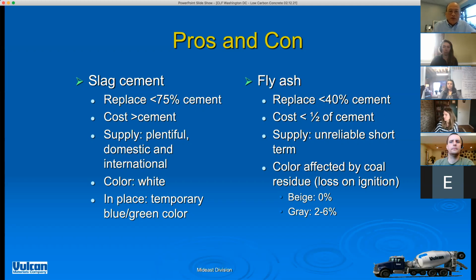Going to the right-hand side, looking at the fly ash comparison, locally fly ash has been used up to 40% replacement of cement. The cost is half that of cement, so it's a relatively inexpensive material. The unfortunate part is that the supply, at least in the short term, is rather unreliable. If the power plant doesn't burn coal, then we don't get it. Locally, we do get it from the formerly PEPCO plant.